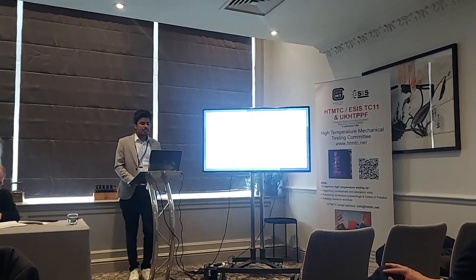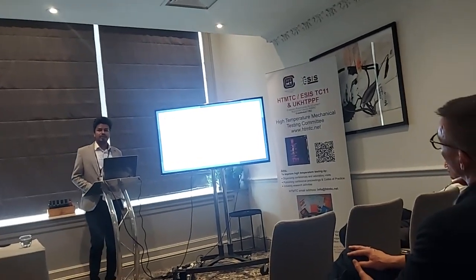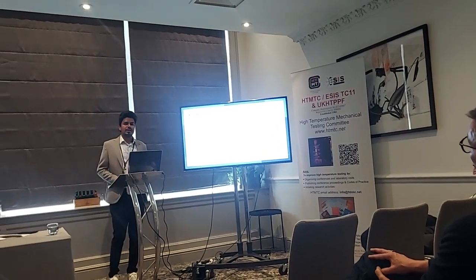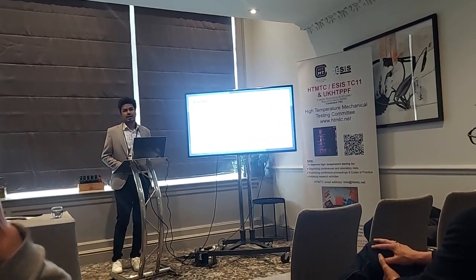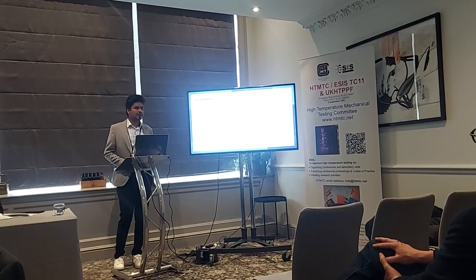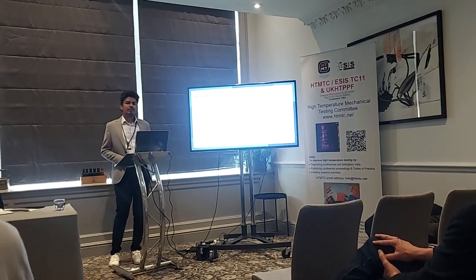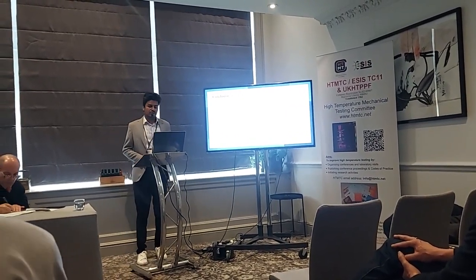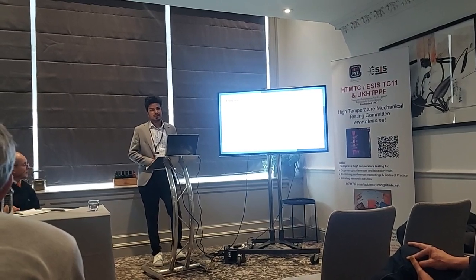In conclusion: the results showed that the creep parameters obtained from SPCT were generally consistent with those obtained from uniaxial tests, indicating that SPCT can be used as an alternative method for the evaluation of conventional creep parameters. The Zhao model is found to be the most accurate in the prediction of creep parameters. The accuracy of creep behavior assessment is influenced by the location of measurement, with the upper node of the center location providing the most accurate and reliable results. Thank you.